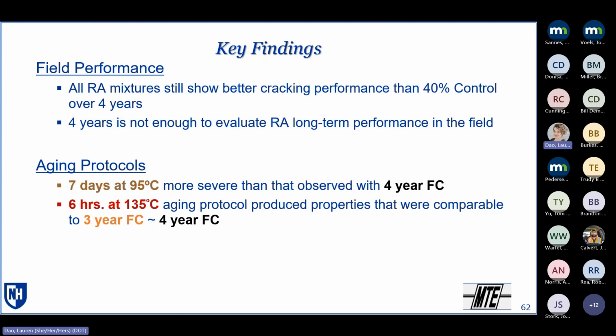That 7 days at 95 degrees C definitely is more severe than what we've seen so far with the 4-year field cores. The 6 hours at 135, based on the different binder properties and mixture properties that we're looking at, is really comparable to 3 to 4 years of aging in the field. And again, that's based on that top half inch of the field core. So it's the very surface. So it's more extreme aging.